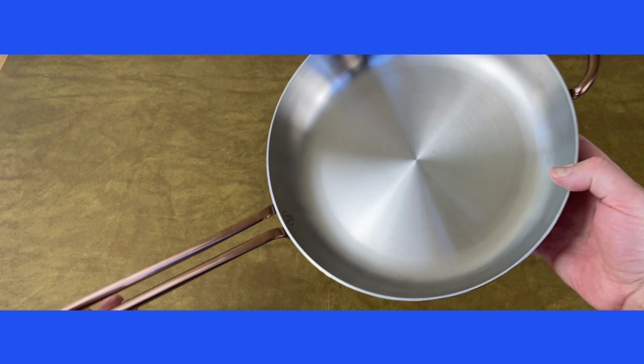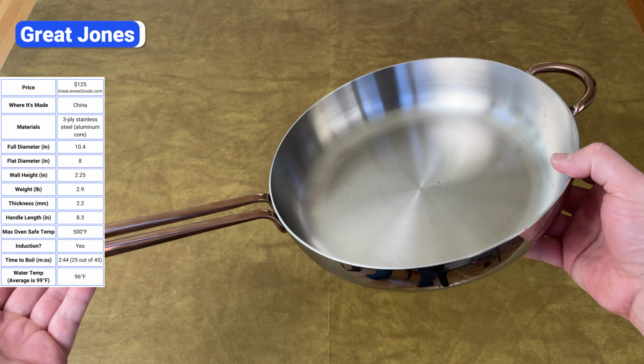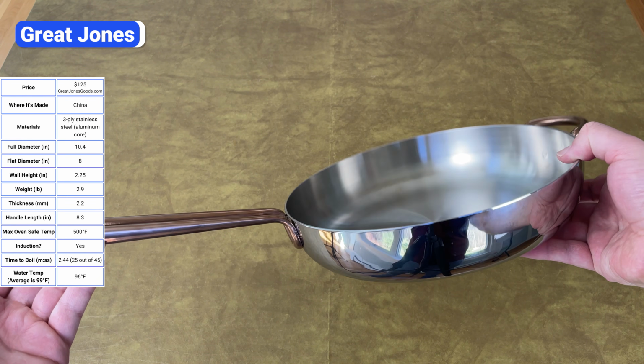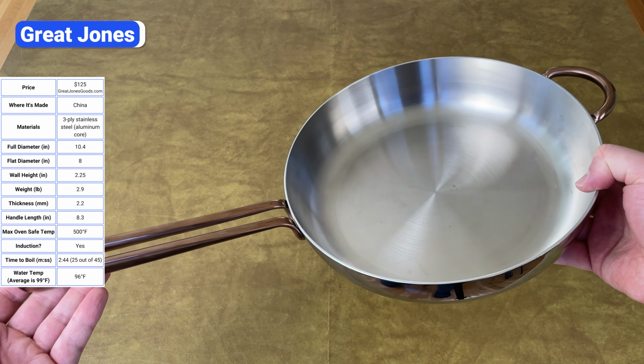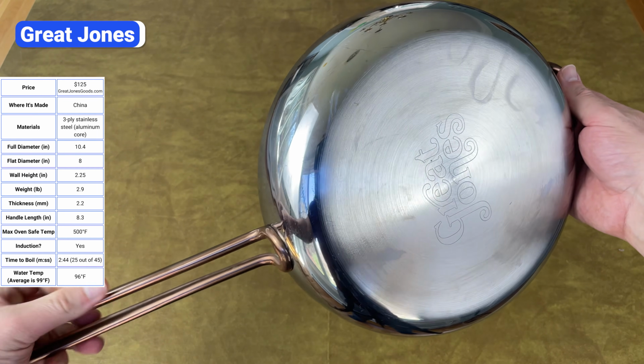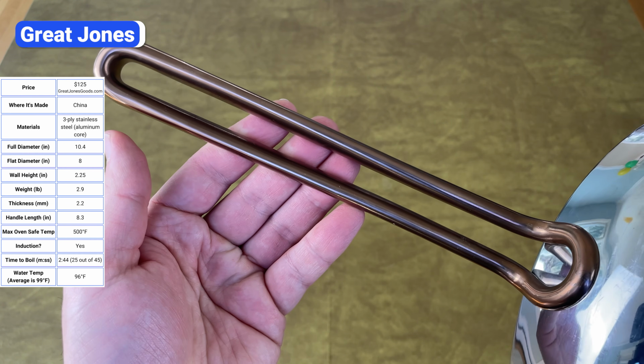At 2.2 millimeters, the walls of the Great Jones stainless steel pan are thinner than average. As a result, it's one of the worst performing pans in my heat retention test. Although the looped handle looks nice, it's not comfortable and it's a pain to clean.